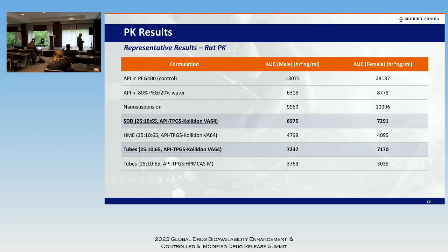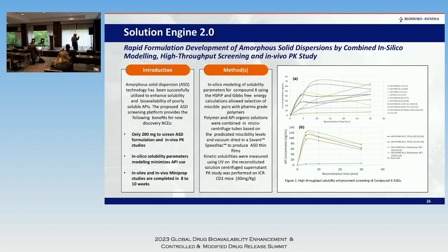As you can see, the evaporation of the solvent using the film casting process gives the same area under the curve. Basically, it's a validated system showing you that you can get the same bioavailability from that system as spray drying. So this means that the system is validated for us, and this is what we utilize at these early stages of development to develop our formulations. This is a poster that we published further at AAPS.